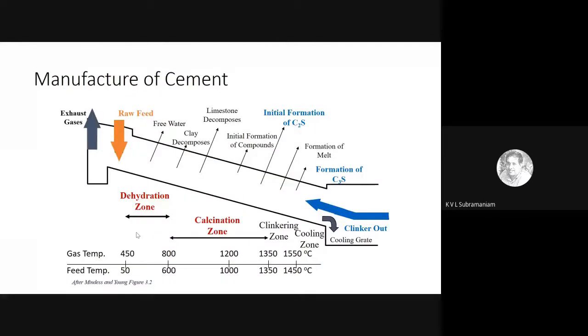Now, what happens in the manufacture of cement? This is a schematic of the cement kiln. Here we have the top end, where I'm showing the raw feed enters the kiln. Raw feed consisting of limestone and clay. This enters into the kiln, and at the other end of the kiln, which is this sloping cylinder, we have a source of heat. It's usually an open flame, and that is extremely hot.